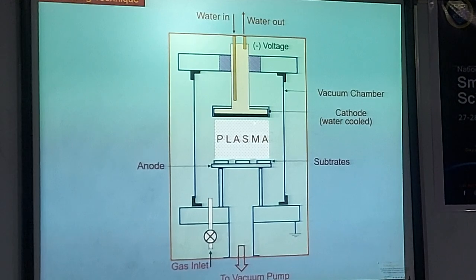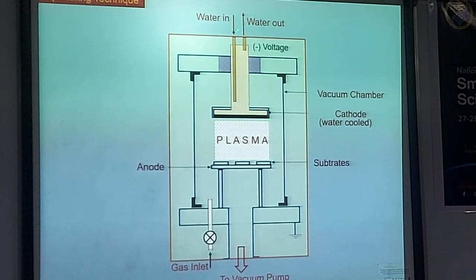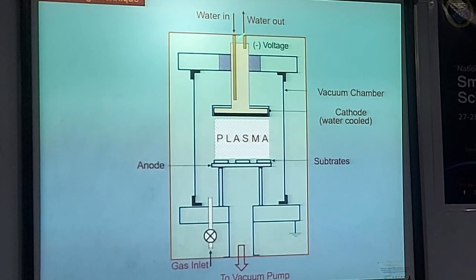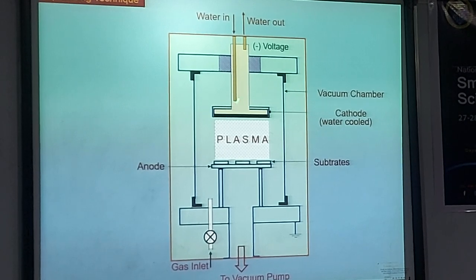Similar to evaporation, there is also a technique called sputtering. This is a schematic of the sputtering technique. It has its own advantages, especially if you need very good adhesion for the film. In mechanical engineering, we go for sputtering. Of course, even for sensor development, etc. So in this case, instead of heating the material to bring it to the vapor state, what we do is, the material to be deposited is taken in the form of a target.